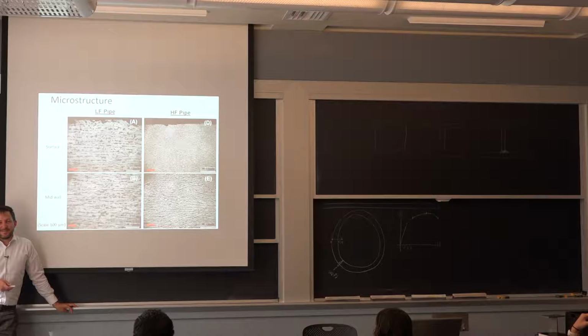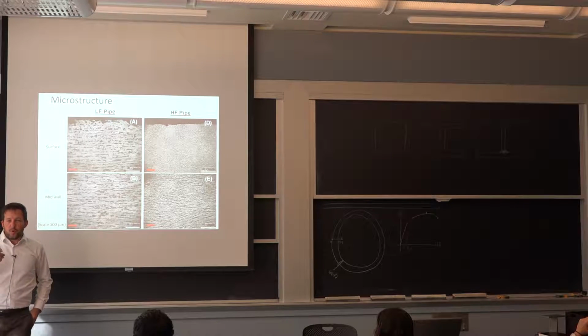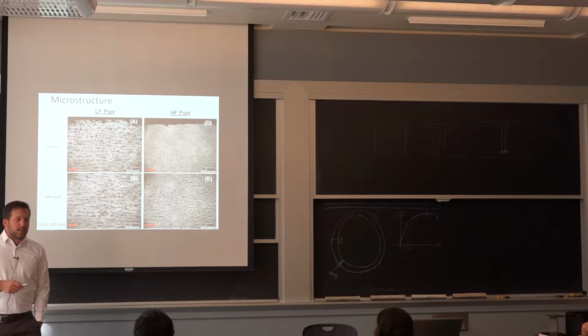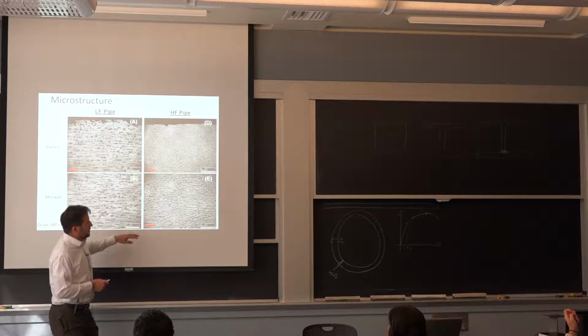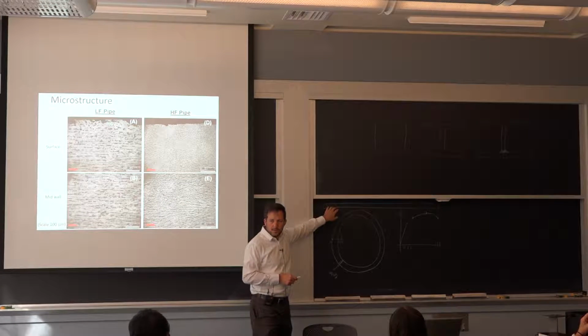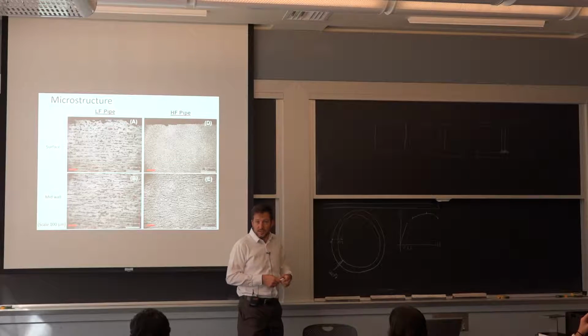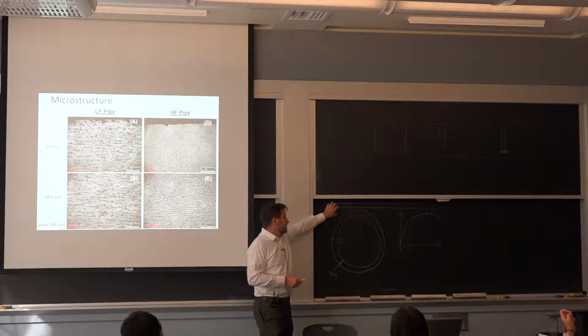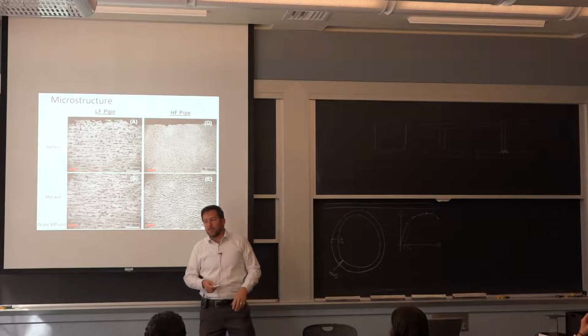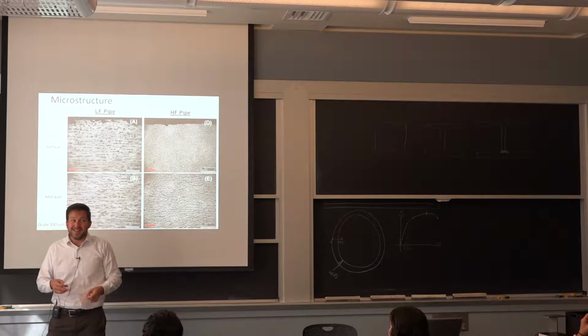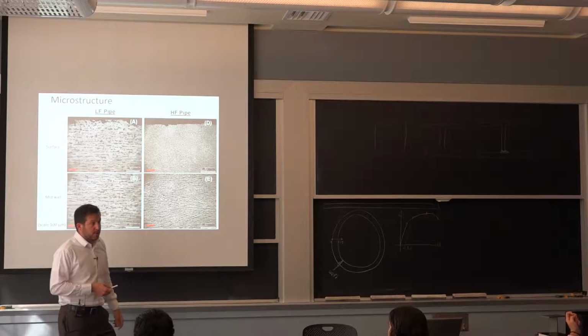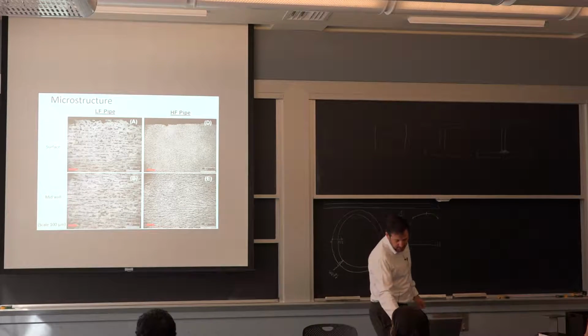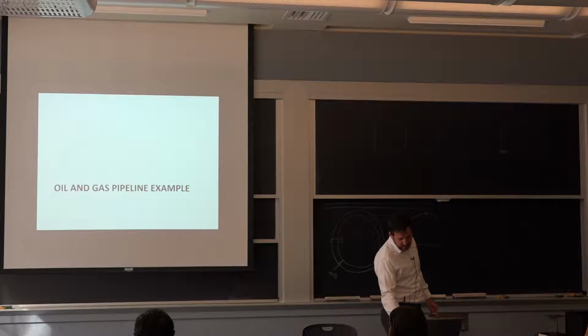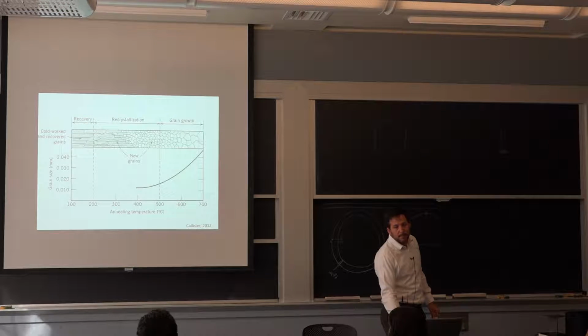Yes? So when you're trying to quench it, doesn't it take time for the temperature to drop to the middle of the wall? Yes. It wasn't quenched. So the plate here started very homogeneous. Otherwise, yes, that would be one reason for having variation. In this case, it started as a flat, they bent it, and then we went through the documentation and they did an annealing procedure, just like the graph I showed you at the beginning. So it wasn't enough to change the phase. It was just enough to do this type of thing.